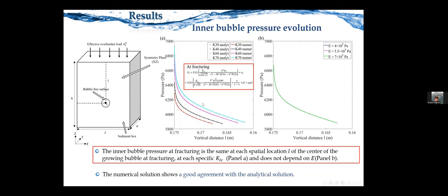The situation would differ between the different properties of sediment, the fracture toughness. But if you look again into this formula, you would see that there is no dependence on the Young's modulus. Actually, that means that this pressure does not depend on the Young's modulus at all, only on the fracture toughness. So those are very important results.